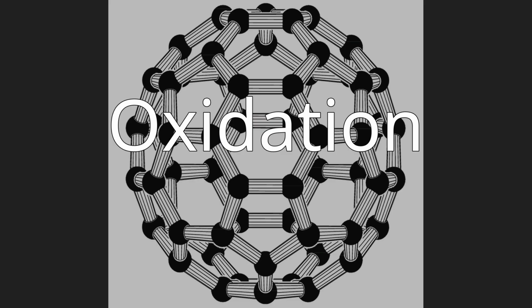Oxidation. The purification and oxidation of carbon nanotubes, CNT, has been well represented in literature. These processes were essential for low-yield production of carbon nanotubes, where carbon particles, amorphous carbon particles, and coatings comprised a significant percentage of the overall material, and are still important for the introduction of surface functional groups. During acid oxidation, the carbon-carbon bonded network of the graphitic layers is broken, allowing the introduction of oxygen units in the form of carboxyl, phenolic, and lactone groups, which have been extensively exploited for further chemical functionalization.